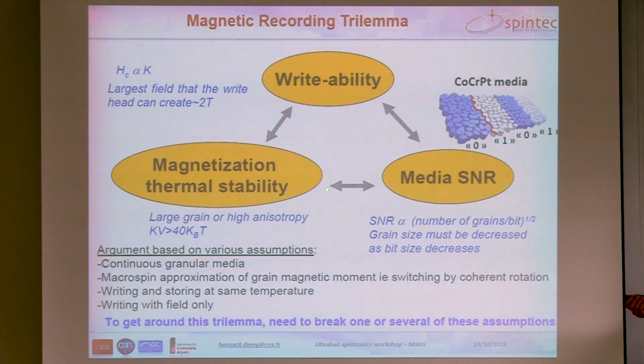But now we have this problem of thermal stability of the grains, because you know that in order to stay above the superparamagnetic limit, we need to fulfill this relationship where K is the anisotropy of the grain, V is the volume of the grain, and here we have the thermal activation energy. So if we reduce the volume of the grain, because we want to increase the areal density, we need to increase the anisotropy in order to maintain this relationship.